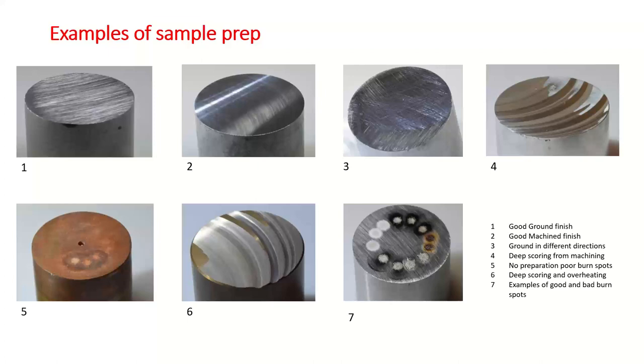Overheating of the sample: if you cut too deep, examples of this are 6 and 4, you can actually see where the tool has cut into the sample so much it's created an extra amount of heat, and the sample's actually gone blue. So that's going to give you poor results, and certainly on this one, being a very uneven surface, you're not going to get a nice flat and good response from there.